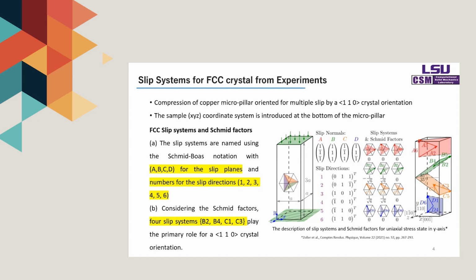Using the Schmid-Boas notation, A, B, C, D denote the slip planes, and numbers denote the slip directions 1 through 6. Considering the Schmid factors for slip systems, B2, B4, C1, C3 play the primary role for the 110 crystal orientation.